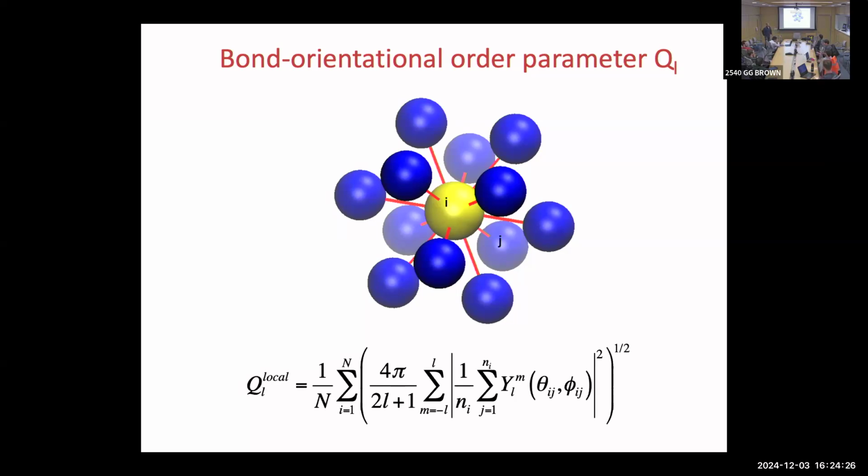Okay, so your R is kind of thresholded. My neighbors are well defined, my J's are first neighbors of I, because if you averaged over every J, you wouldn't get anything. So is this essentially giving you a packing fraction? No, that is important. This is getting at whether my neighbors are in crystalline positions. It's relatively independent of packing fraction, because you can do a Voronoi tessellation for any packing fraction. But you can define local packing fractions, which could be interesting.